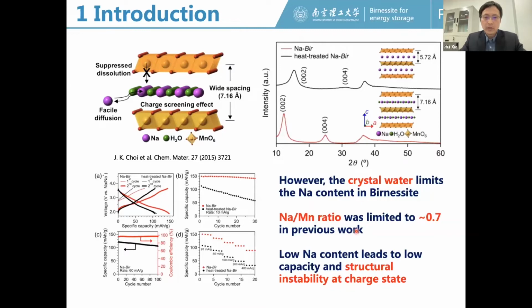If the sodium content is low, this layered structure actually is not very stable, especially at the charge state. It is similar to lithium cobalt oxide. If we take all the lithium out, this oxide is not stable at the charge state. So this is the problem.